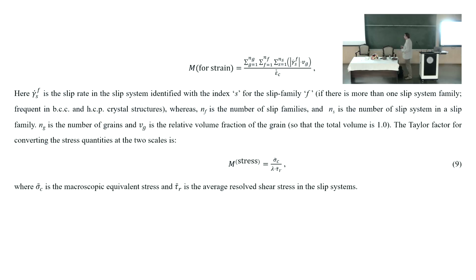Well, it turns out that this Taylor factor business is based on the energy calculation. So you calculate the plastic energy in two different ways. Grain by grain, and you add them together. That's one energy. Then you can calculate the energy in your polycrystal by multiplying macroscopic quantities. The energy is calculated by stress multiplied with strain rate. It's a plastic power, and you can calculate it in two ways.